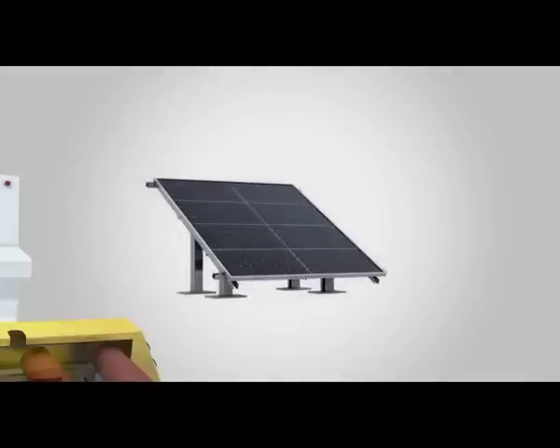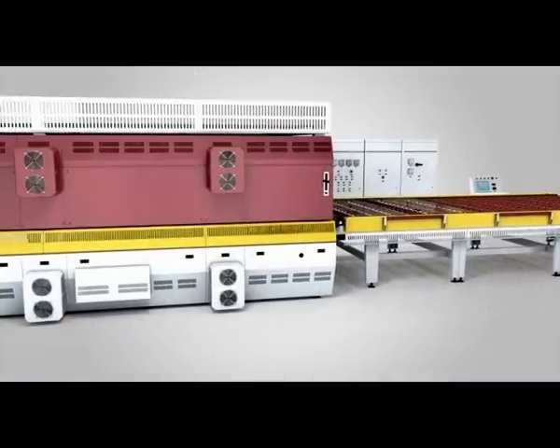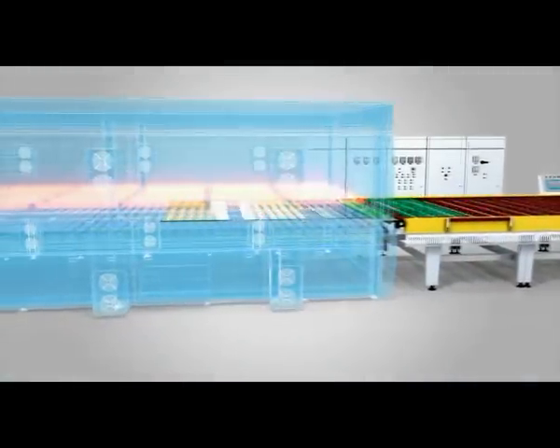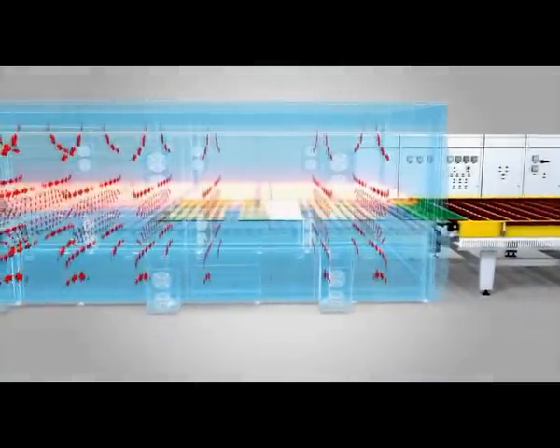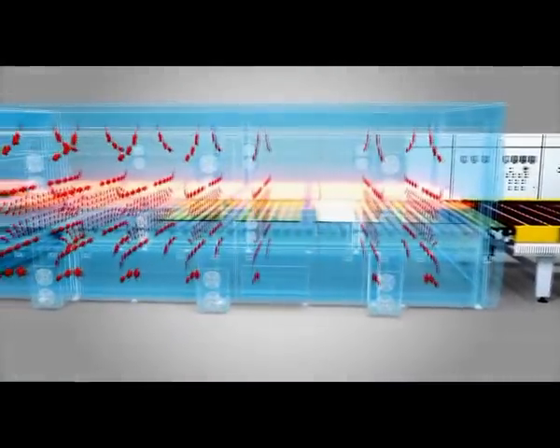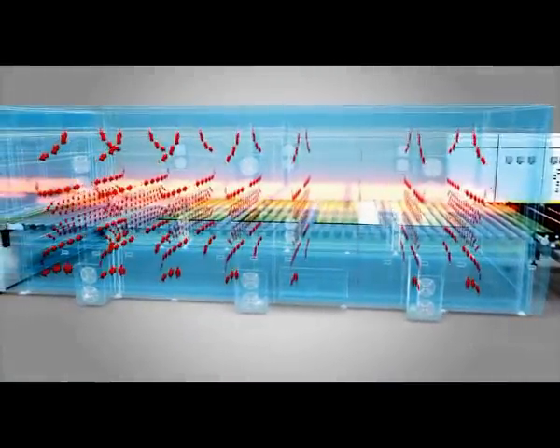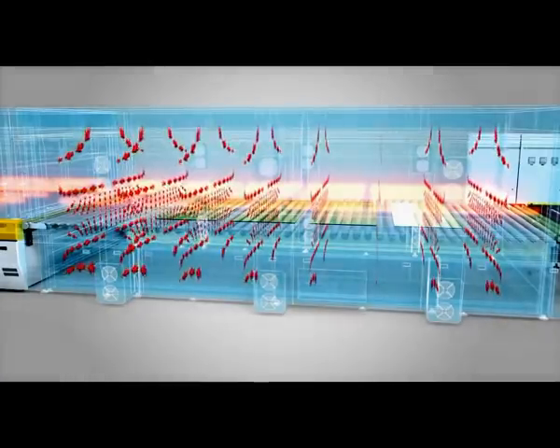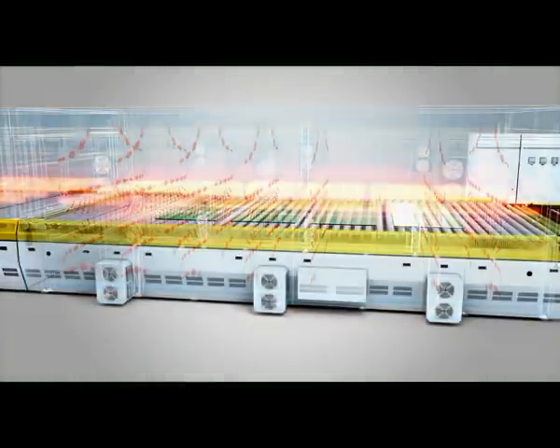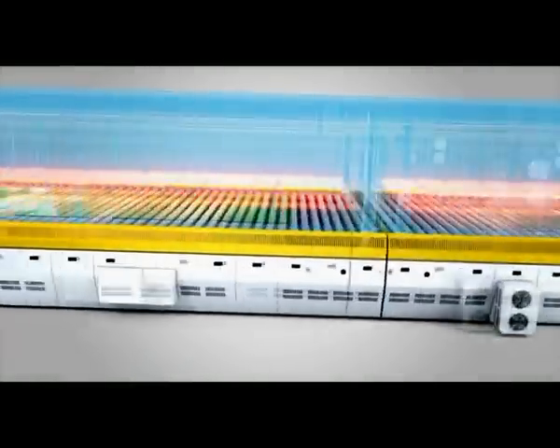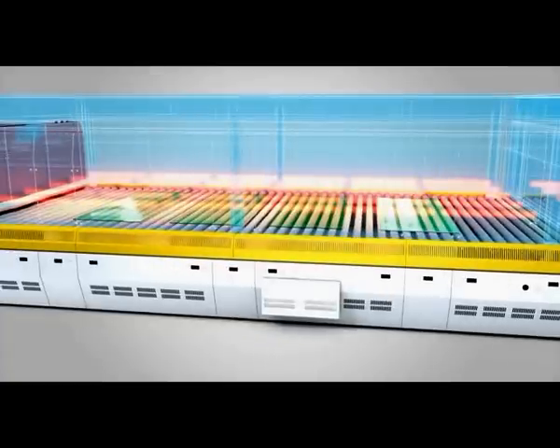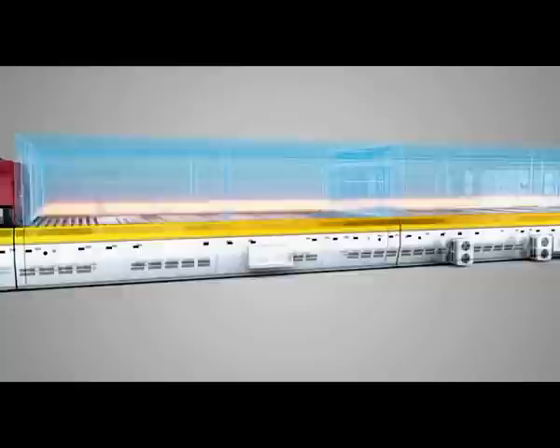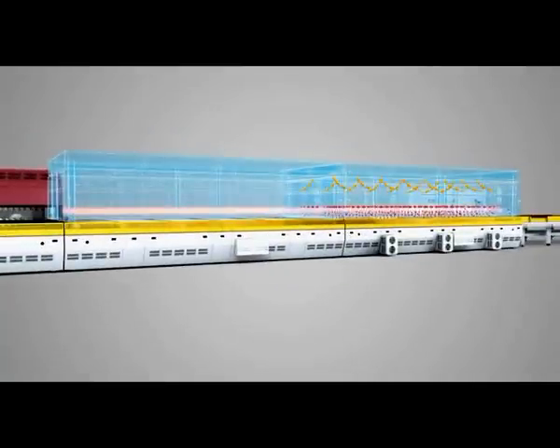Higher heating uniformity and superior glass quality. In pre-heating chamber, glass is heated to 400 to 500 degrees Celsius through forced convection heating system. In second heating chamber, glass is heated to target temperature through radiation heating system.